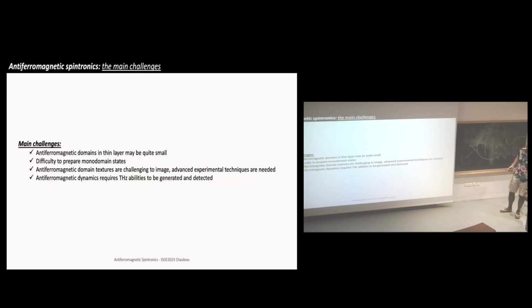So there is some kind of take-home message. First of all, working with antiferromagnetic material is nice, but it's quite challenging. Especially, most of the time you work with antiferromagnetic domains in thin layers, which can be quite small, so you need techniques to be able to visualize them. So it's not to be neglected, we have some effort to put into imaging directly the antiferromagnetic vectors. In the same way, there is a huge amount of work to do to prepare monodomain states, because they are not easy to handle. We cannot handle them with a magnetic field. So it's very difficult, and it's a lot of material science and material engineering.